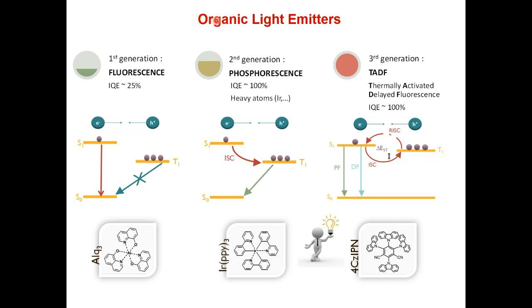And so in those light-emitting devices, you generate 25% of singlet, 75% of triplet, but then thanks to this coupling, you can have a transition from S1 to T1, and then you can exploit all the T1 for light emission, and you have 100% efficiency if everything goes well. Of course, there are other problems, but you can exploit all the excitations that have been generated. So this is basically what you find right now in many, many devices, typically sold in Japan, like mobile phones, cameras, any kind of music application, a reader, you will find this kind of material.